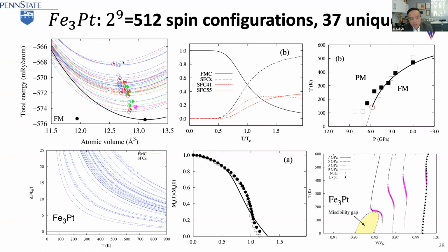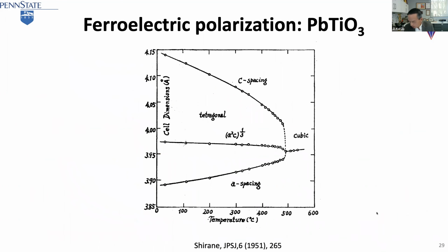It's because the metastable configurations have a smaller volume. Everybody has a positive thermal expansion, but because smaller volumes replace bigger volumes, the total volume may decrease. That's called emergent behavior. Everybody has a positive volume increase with temperature, but put them together, they have a negative volume increase with temperature in this range. At the critical point, the volume change becomes infinitely negative. That's a derivative of this curve. And in that case, I do have another example.